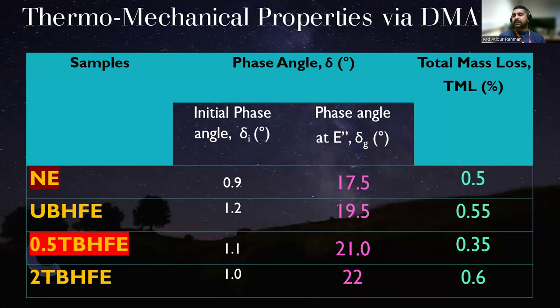For neat epoxy, corresponding to the peak loss modulus, the value was 17.5 degree. For untreated, 19.5 degree. However, for the treated, you can see 21 and 22, which represents a higher viscoelastic property compared to the neat epoxy, and that's why it affects the damping factor value. And total mass loss was another property. We can predict how the material will sustain its mass or stability in that particular environment. So we can see that 0.5TBHFE got the highest stability, with a loss of only 0.35% during the whole event.